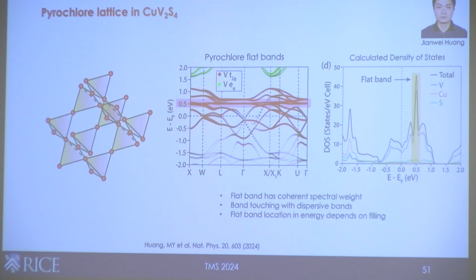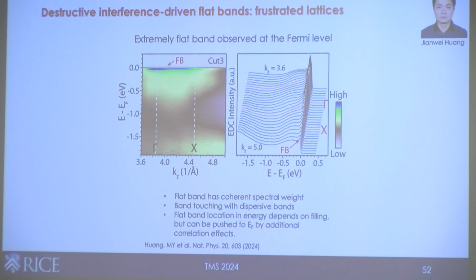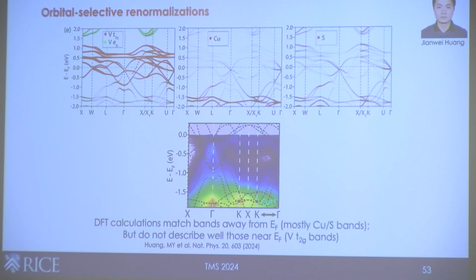But there's a puzzle, because if you remember from DFT, this thing is half an eV above the Fermi level. Why do we see it at the Fermi level? Which is kind of interesting. If we look farther out in the band structure, we notice that if you stay away from the Fermi level, all of these features actually have reasonable agreement with DFT. It turns out these are the copper sulfur bands farther away from the Fermi level. It's just the stuff near the Fermi level that does not match well with DFT. And this immediately reminded us of the iron pnictide stuff that we worked on earlier, suggesting possibly there's some sort of orbital-dependent correlation effects that could be missing in the calculation for the vanadium sublattice.